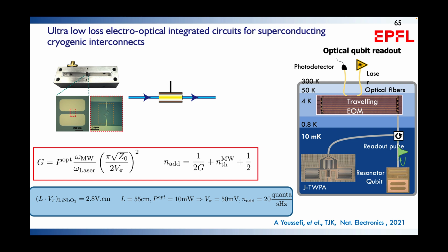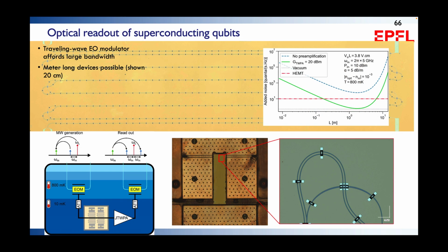The only way to realize this is to have a very long interaction length. And this can be achieved if you take, say, a 55 centimeter lithium niobate or lithium tantalate integrated photonic circuit. With this you can get switching voltages in the tens of millivolts. This is an example of such a device. It's a 20 centimeter long device in lithium niobate, and this can operate, if you go to 1 meter path length, with a noise figure that's very close to and even below that of the HEMT amplifier.